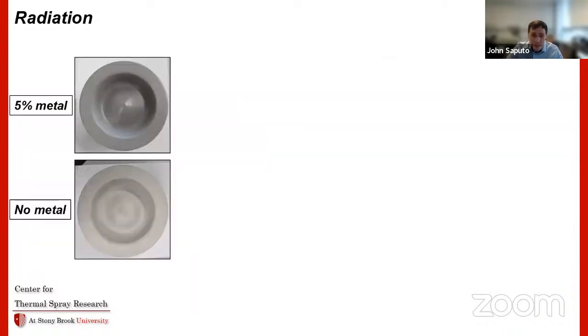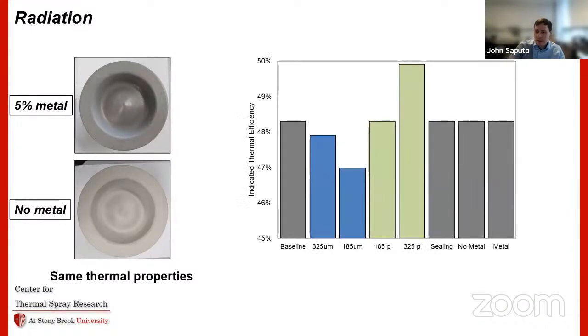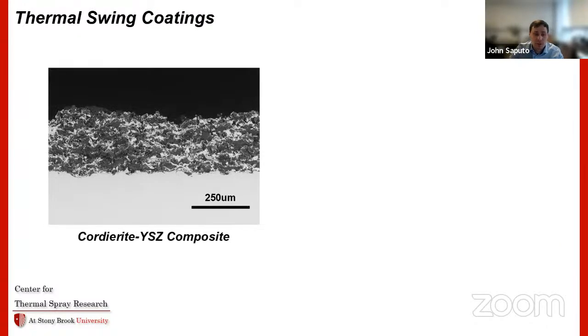So again, you can take a piston with 5% metal volume fraction like we tested before, remove that, and tune the thermal properties, the conductivity of these systems to be about the same, and do performance testing, and you see absolutely no change, which is interesting again. So we decided to go from this to the thing that everybody's been driving towards in the new system, which is these thermal swing materials.